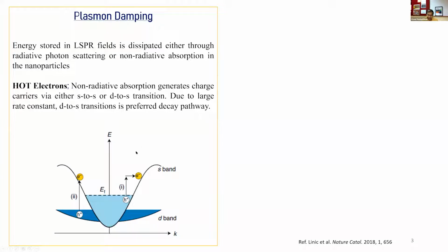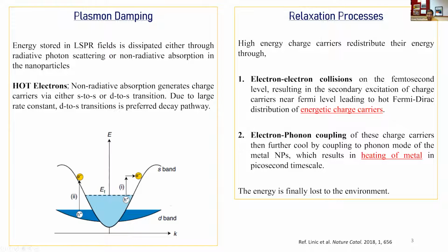However, the lifetime of these hot electrons is a few femtoseconds, so ideally you may not be able to use them. But during the relaxation processes, these hot electrons undergo collision with the electrons at the Fermi level. Because of this electron-electron collision, you create a secondary population of hot electrons, known as hot Fermi-Dirac distribution. These hot electrons have a better lifetime and can be injected into the CO2 or some other reactant during the catalysis.